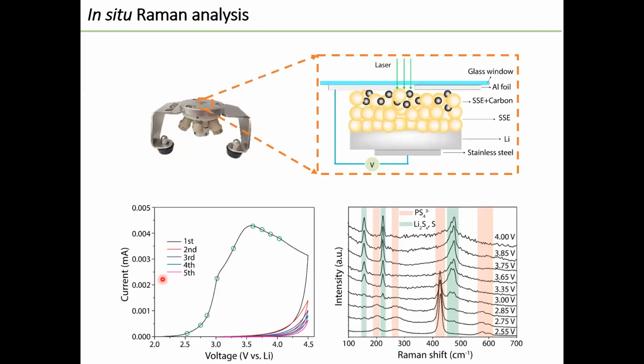Next, we analyze the electrochemical stability window of our electrolyte. We conducted an in situ Raman to test the stability window. The setup is shown here. There is an optical window which allows the laser to transmit and allows the Raman signal to be collected. When running a CV test, we can find obvious oxidation peaks appeared in the first cycle, and the decomposition products are stable in this voltage range because oxidation only happened in the first cycle.